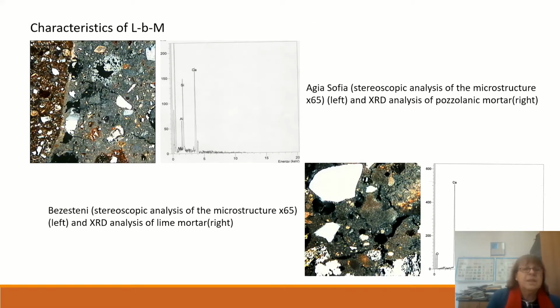Here you can see the microstructure of two original mortars from a Byzantine-Ottoman monument and from the Hagia Sophia Byzantine monument. You can see at the right that we have in the matrix many pores and cracks, while in the case of the lime-pozzolan mortar in the Byzantine monument Hagia Sophia, we have a more compact matrix and a very good interface between matrix and crushed brick.